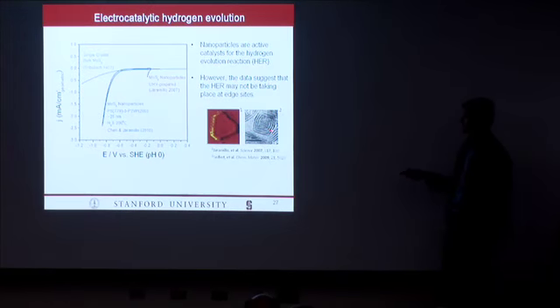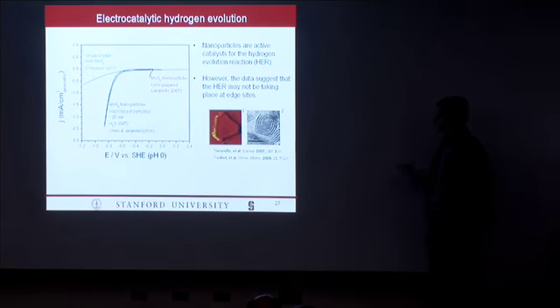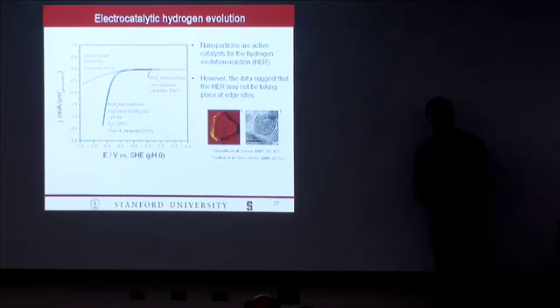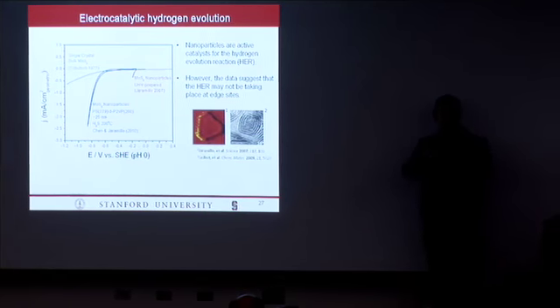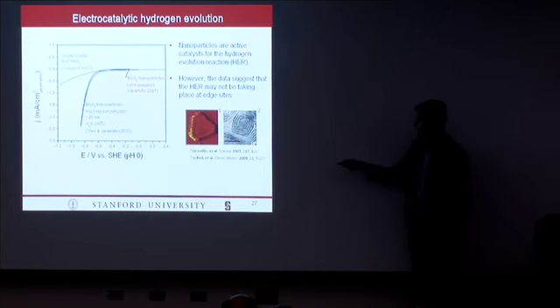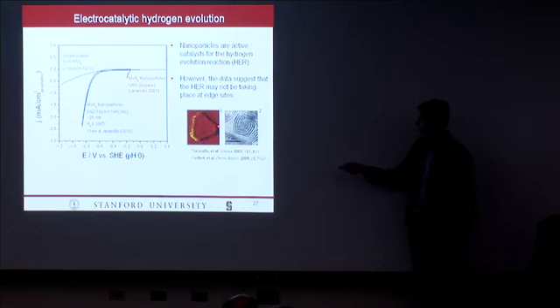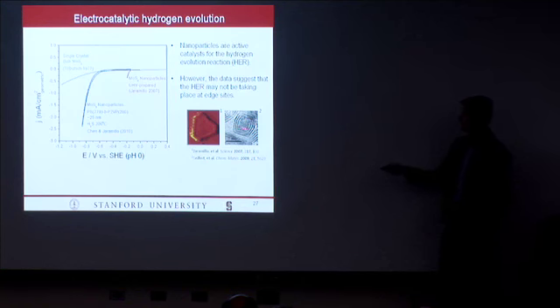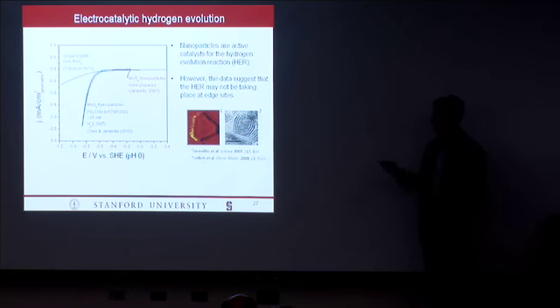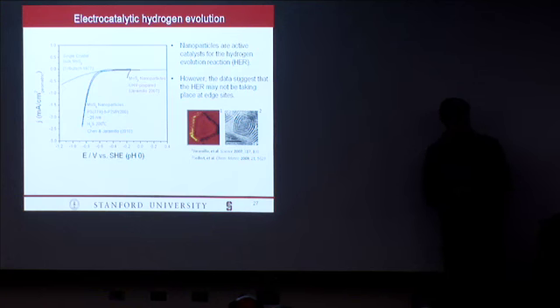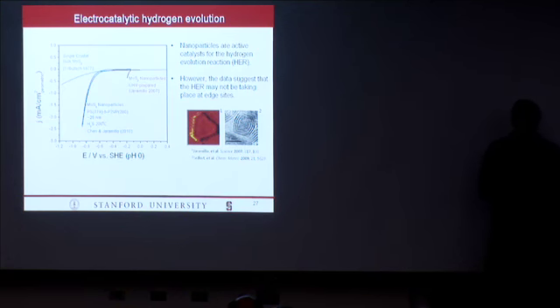And this is some recent work that was published from a group in Israel, in which case they find that molybdenum sulfide often likes to fold up over on itself. And the work that we had done in Denmark, we had really elucidated that it's the edges of the molybdenum sulfide that are active for hydrogen evolution. If this thing folds up and forms an onion-like structure, you don't have edge sites anymore. So this is something that we're looking to ultimately control. We think we can improve that onset into this vicinity so long as we can keep these nanoparticles unfolded.